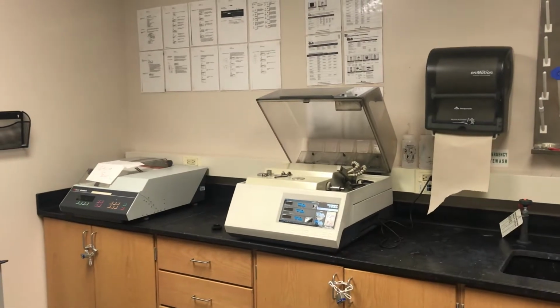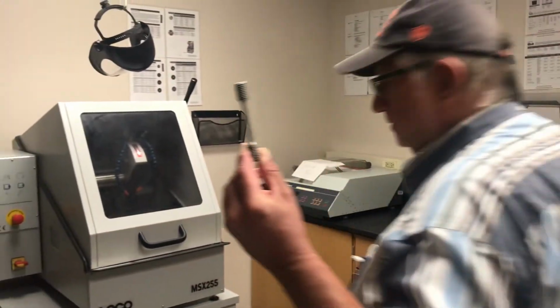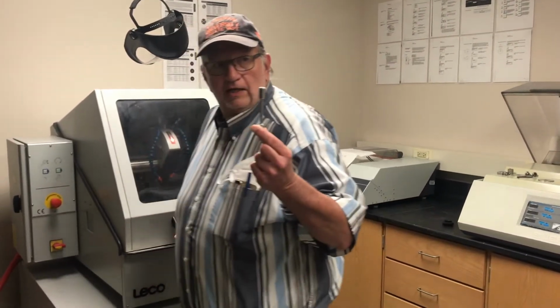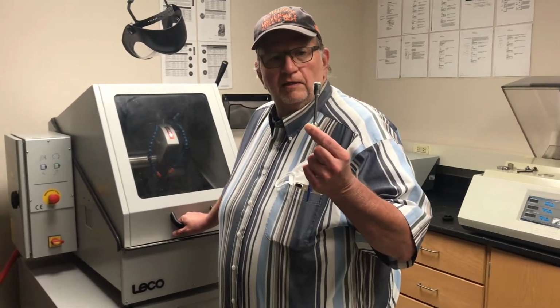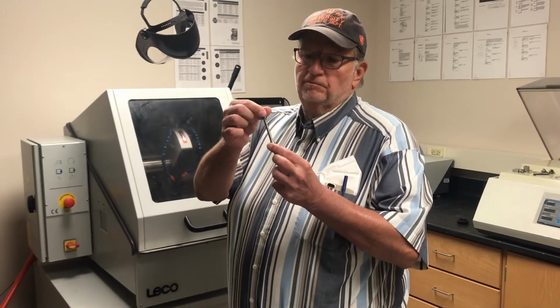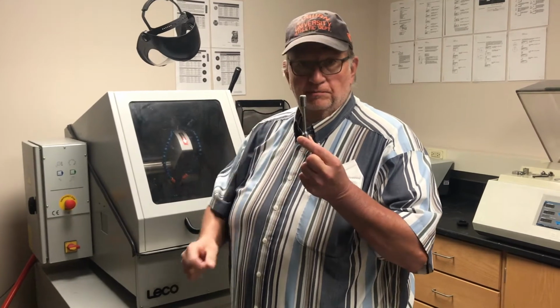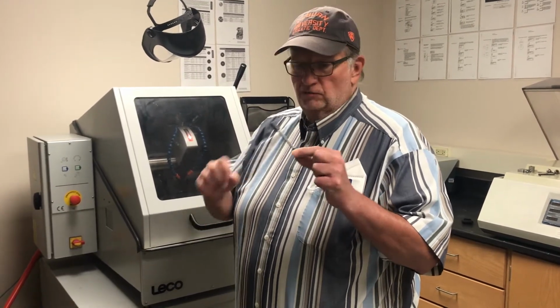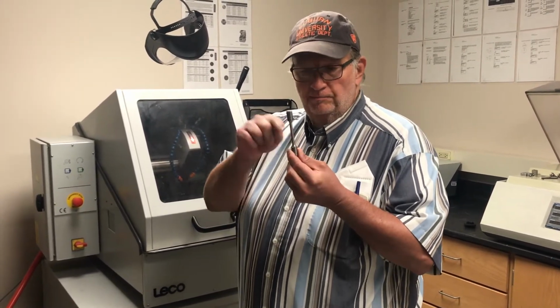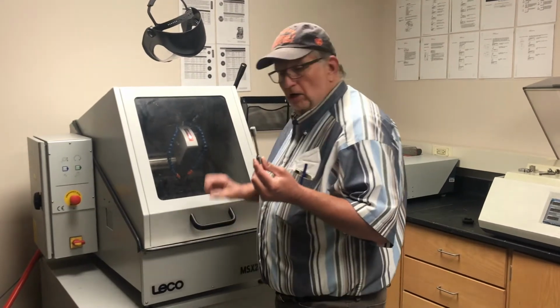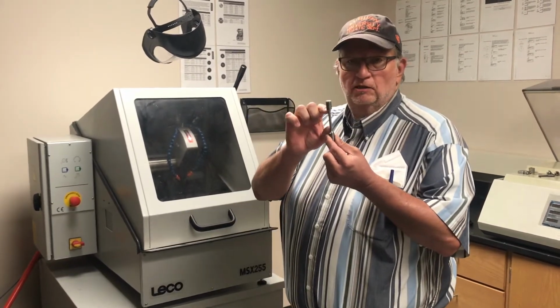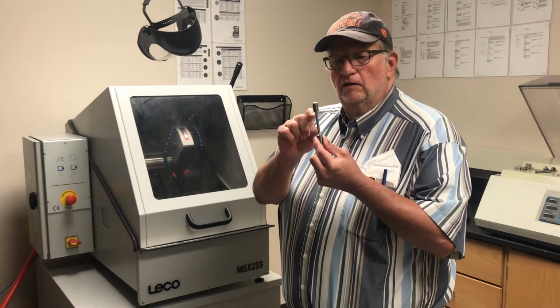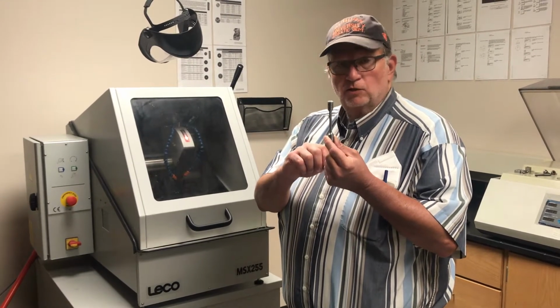Let me grab my sample. This is a tensile sample. You'll see more of that later. But it's threaded on both ends and the test region is in the middle. After we do our test, in which case the sample would normally be broken, we want to cut a sample of the test region and analyze that to get the microstructure.